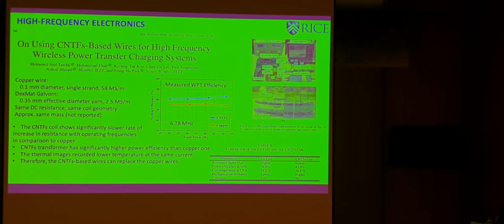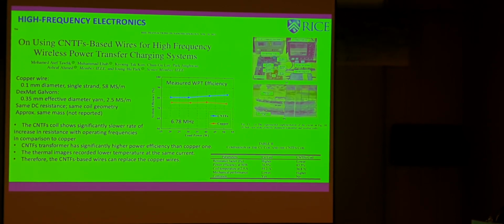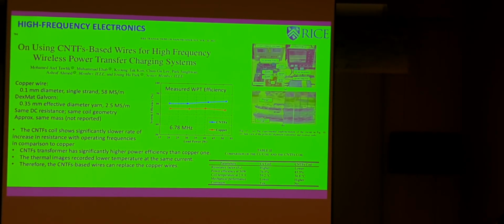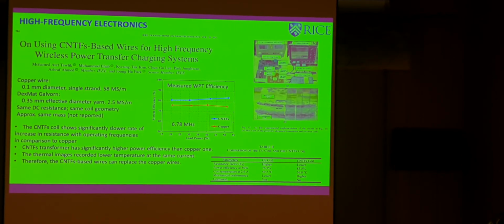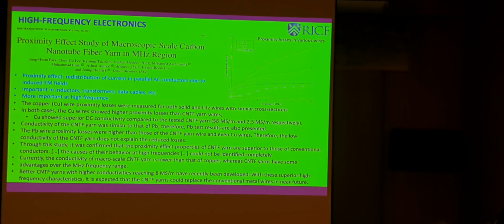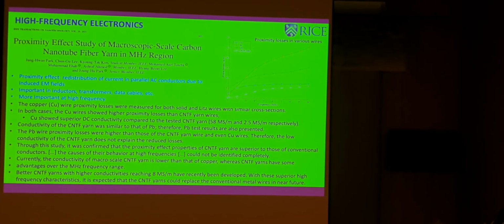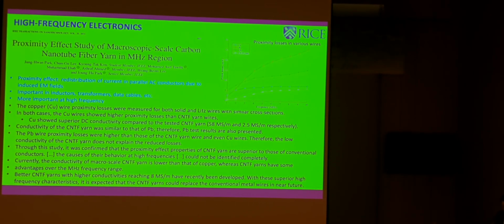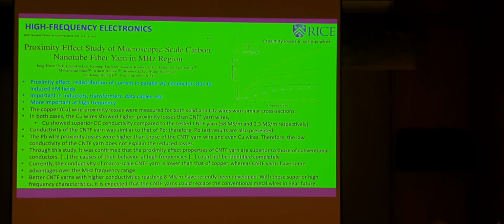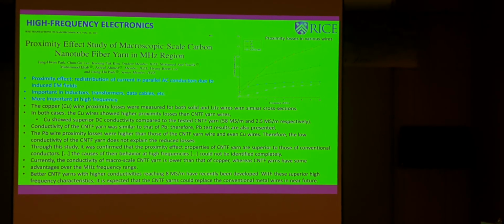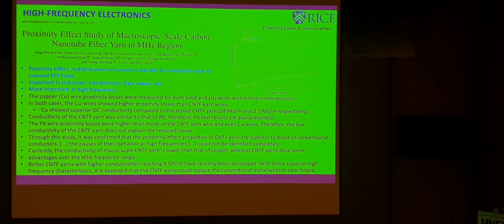Other work, this is out of Jonghyun Park here in South Korea. This is a group that has power electronics, and they saw that the carbon nanotube fibers were behaving better than copper, higher efficiency in a situation where you want to do wireless charging, wireless power transfer. Or another situation where they looked at proximity effects. So proximity effects is when you have two wires that are almost parallel, and the AC current in one wire generates a magnetic field that interferes with the neighboring wire, and they saw significantly lower proximity effect in nanotube fibers compared to metals. And it was not due to conductivity, because they took lead, which had about the same conductivity as carbon nanotube fibers, and they saw a different behavior.